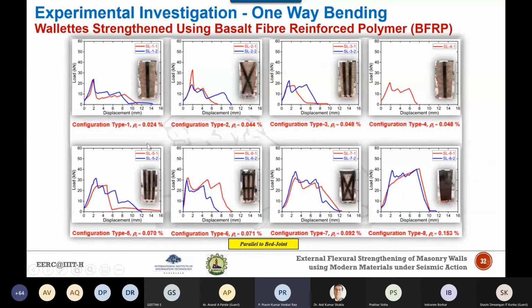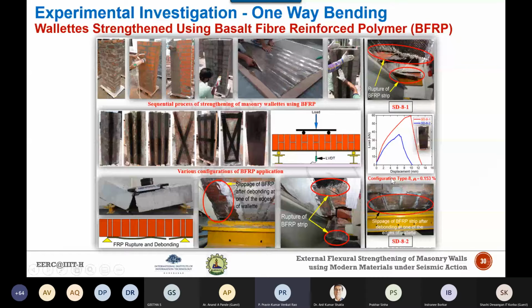40 kilonewtons. But in FRP, three different types of failure modes have been observed. Either the FRP rupture has taken place, which is attributed to relatively better bond characteristics. Second is basically due to the debonding. This is also a rupture failure. Here you can see that there is a debonding, which is followed by the slippage of this FRP due to one of the edges of the wallets.